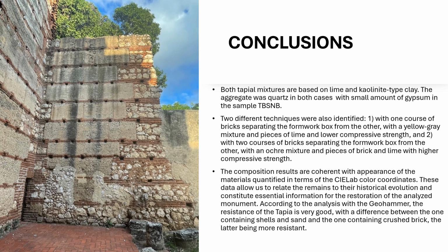We can conclude that both tapial mixtures are based on lime and kaolinite type clay, with an aggregate of quartz in both cases, with a small amount of gypsum in the sample TBSNB. Two different techniques were also identified: one with one course of bricks separating the formwork boxes, with a yellow-gray mixture and pieces of lime and lower compressive strength, and another with two courses of bricks separating the formwork boxes, with an ochre mixture and pieces of bricks and lime with higher compressive strength.